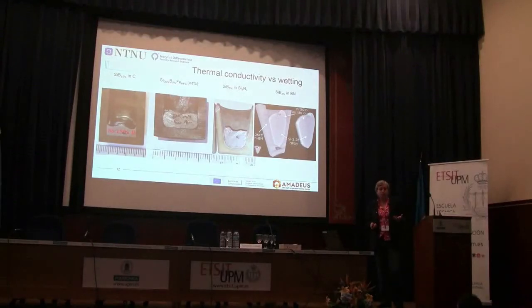Another thing when it comes to thermal conductivity: we said we want the heat to go through the solid material, through the container wall and down into a cell. So the transfer between the phase change material and the crucible is very important. We need a good wetting in a solid state between the two materials, because otherwise you will lose thermal conductivity. So that is also dependent on the wetting. Here we have an alloy with iron, which is not wetting very well, and this will probably affect the thermal conductivity as well.